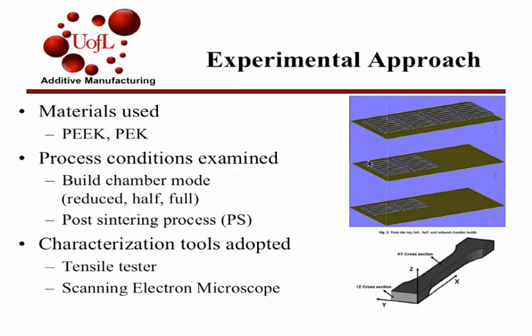In this paper, the process conditions that were examined were the build chamber mode. So they have a half, a reduced, and a full chamber. As you can see here, this is the reduced chamber, this is the half chamber, and this is the full chamber. The other thing that was being examined was the post-sintering process, which is just when, after you print a layer of material, there's an infrared heater at the very top of the machine, and it melts the top layer of the printed layer again, so that you can get rid of any air bubbles and have a smoother surface to print on top of. The characterization tools that were adopted were the tensile tester and a scanning electron microscope.